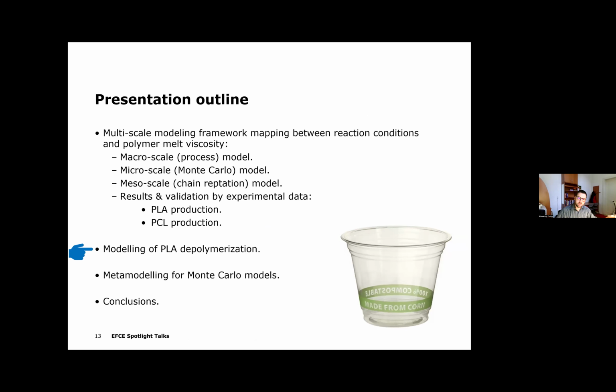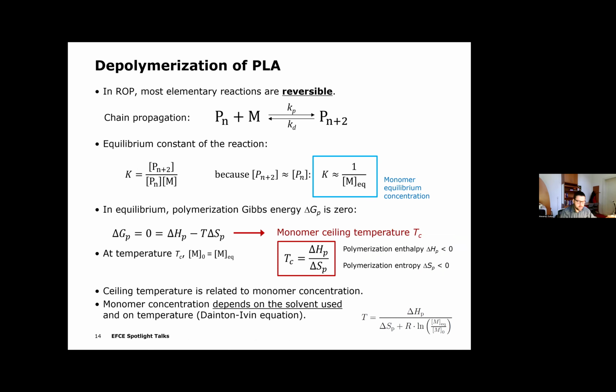Now I would like to move to the second and shorter topic of the presentation, because since we had this Monte Carlo model developed, we were thinking about how we can apply it further. As I already mentioned, in these ring-opening polymerizations, most elementary reactions are reversible. If we take a look at the propagation step, we have an active chain of length n that reacts with a monomer molecule, and since the monomer of PLA is lactide, which is a dimer of lactic acid, after the propagation step is over, the monomer molecule is consumed and the chain is propagated by two lactic acid units, lactoyl units, basically.